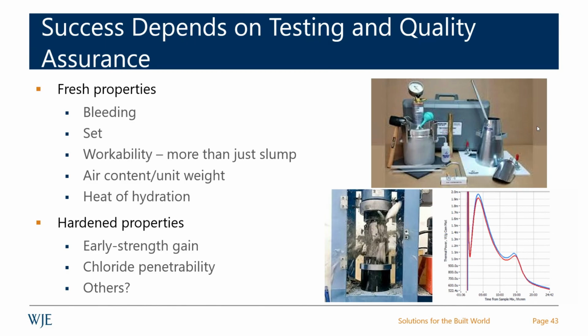We can get great slump numbers, but some of these low clinker mixes, without vibration, just won't move. Air content has become really an issue, and it's not really understood why.